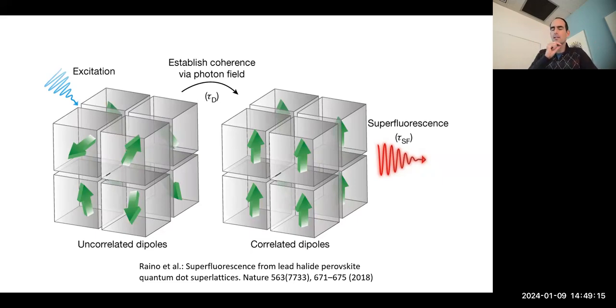Now, the size of the ligand is interesting because if you tune the size, you will actually change the coupling, and potentially you could allow for things like tunneling. So the dipoles, at some point, will become a continuous material, right? It's no longer a quantum dot, it becomes just a bulk crystal or an amorphous crystal or something like this. So there's a kind of tuning that happens if you change the ligand, and some researchers have worked on that. But at the size we've been looking at, these are essentially isolated dipoles.